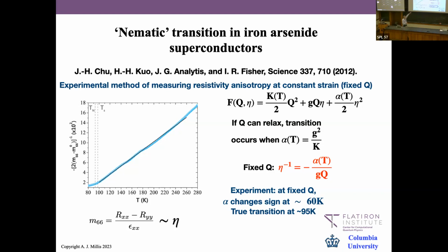Once you're in the ordered state, it's different, because then you have an order parameter which is going to keep doing something else. So then what you're seeing is changes around an ordered state. That's why we only look at temperatures above the transition temperature. Once you're in the ordered state, the analysis has to be different - I've given you an analysis which is only in the disordered state.